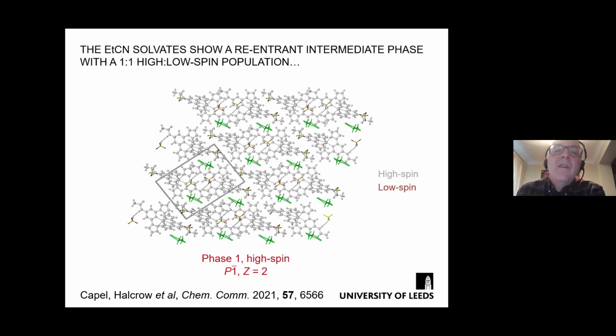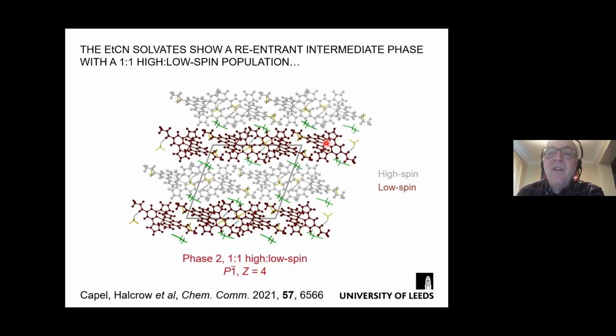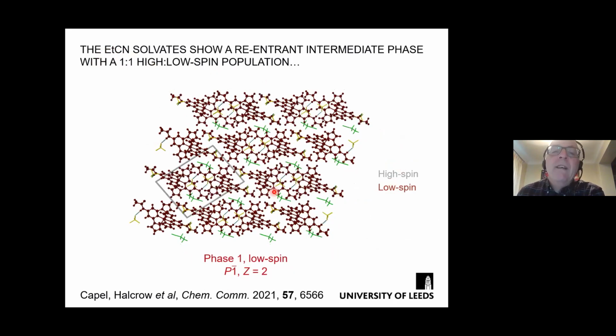So as you might expect, the step in the propionitrile solvates comes because for this solvent, we have an intermediate phase, which is a mixture of high spin and low spin crystals. Same space group, but double the unit cell size. And then when we go down to fully low spin, we regain the original crystal phase. This is quite well-known behavior now for different spin crossover crystals. It's not so interesting. But again, the more interesting question is, why do we only see this behavior with the larger propionitrile solvent?